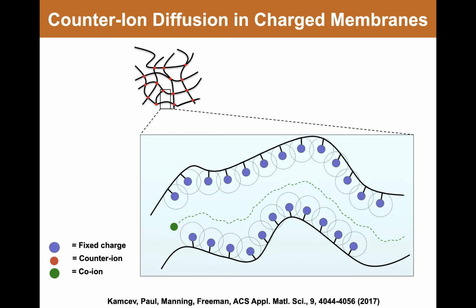Now, for co-ion diffusion, remember the counter-ion diffusion, remember the counter-ions had a somewhat different story. The counter-ions are moving faster than co-ions, under circumstances where that was unusual. That is, in the sulfonate-based cation exchange membrane, we saw sodium ions moving faster than chloride, whereas in aqueous solution and in the anion exchange membranes, chloride always moves faster, always has a higher diffusion coefficient than sodium.